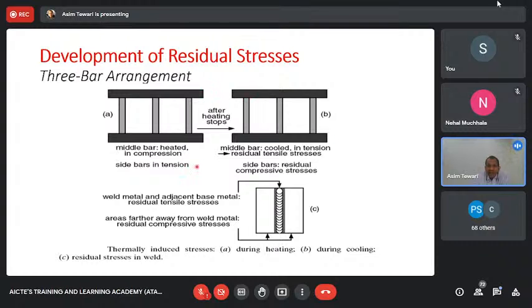So this can be handled by this 3-bar arrangement. Your bar 1, bar 2, bar 3. These are just to show you how this material is being modeled. So we are having the welding gun go from here in the center. And when we do that, the center part will essentially get molten, and the other 2 bars will just get heated up but will not melt.